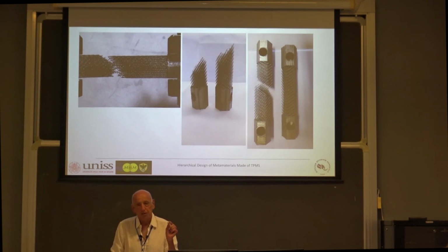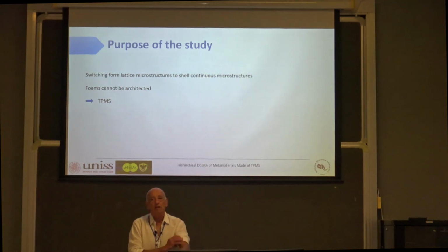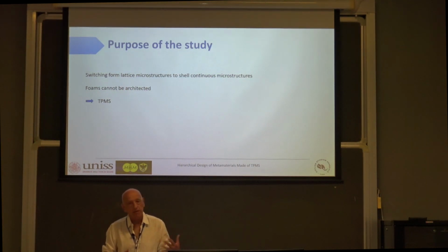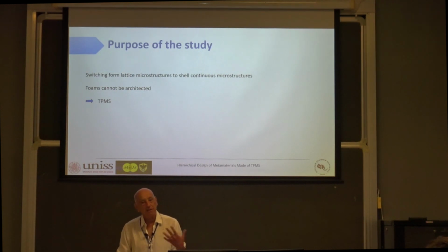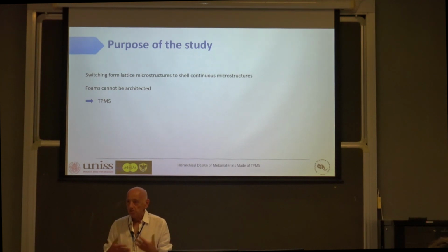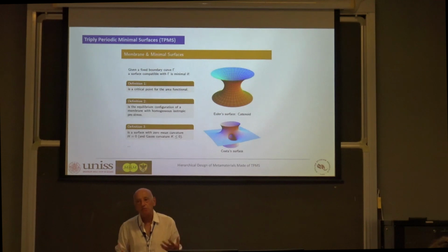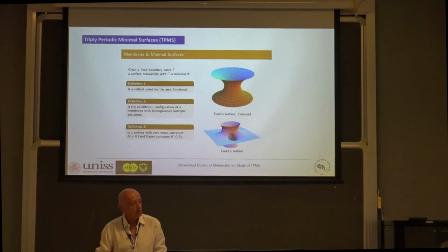And the reason is that the thickness of these microbeams was small, I remember a fraction of a millimeter, so it's comparable with the grain size of the 3D printing process, and they were much more fragile than what we expected from the properties of titanium. So the idea is to switch from lattice microstructure to continuous microstructure made by surface shells. Foam is a possibility, but foams cannot be architected, as the process is random, so it can be nice. So we started trying to see what can be done with triply periodic minimal surfaces.